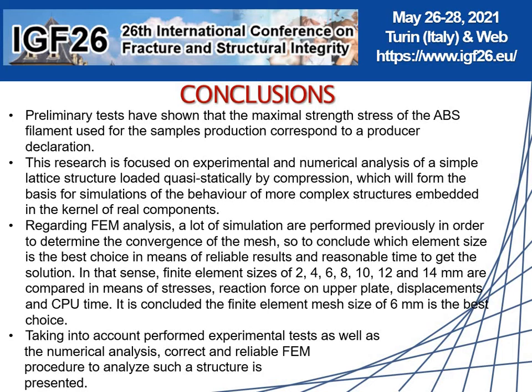Some concluding remarks: Preliminary tests have shown that the maximal strength stress of the ABS filament used for sample production corresponds to the producer's declaration. This research is focused on experimental and numerical analysis of a simple lattice structure loaded quasi-statically by compression, which will form the basis for simulation of more complex structures embedded in the kernel of real components.